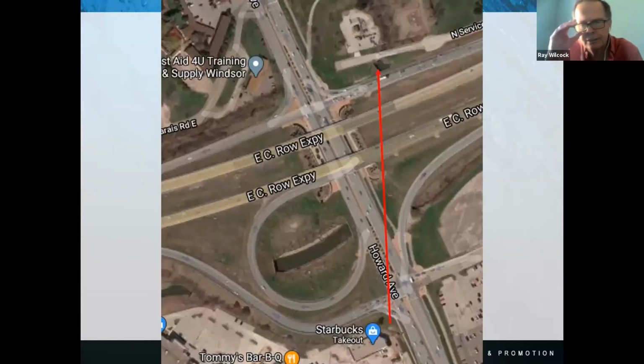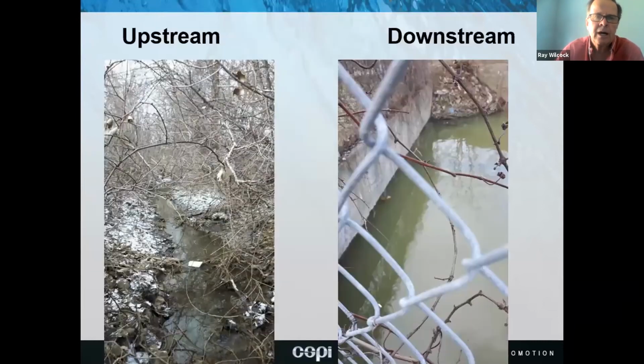And here's an overshot picture of where that storm sewer was. It more or less runs underneath the EC Row Expressway, with Howard Avenue going underneath. It started just where that Starbucks takeout is, and then went all the way out to that outlet you can see across there. Here's a picture of the upstream. It's hard to tell, but that was very corrosive water. You're probably talking about 500 parts per million of chloride, so not very pleasant. And there is the downstream outlet.